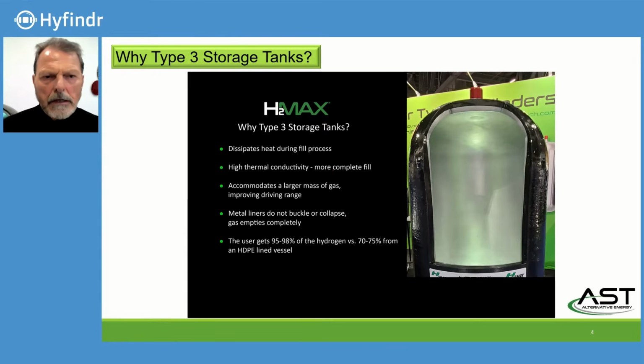The metal liner does not buckle like a plastic liner, so we can completely empty the liner as well. We don't have to leave any gas in to avoid the buckling of the liner. In other words, with tests we have made, long-term tests, we have compared type 3 with type 4 doing the fast filling rate, and the fast filling capacity on a type 3 is up to almost 100%, when the type 4 is below that, at 70-75%.